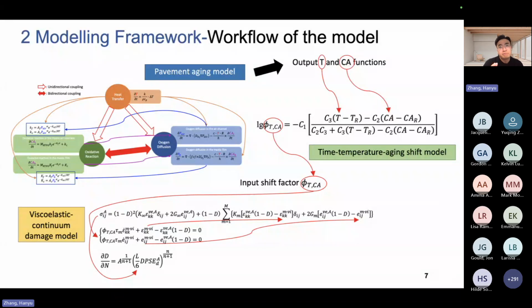So this slide shows the workflow of those different models. First we conducted the pavement aging modeling, and we output the functions of temperature and the carbonyl index, related to the time. It's an evolution function. Then we input those functions into the shift factor. Then we input this time, temperature, and aging shift factor into the viscoelastic continuum damage model. So we can obtain the pavement damage conditions when considering the aging effects.